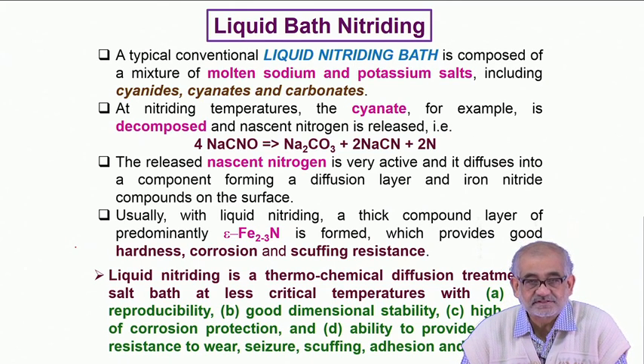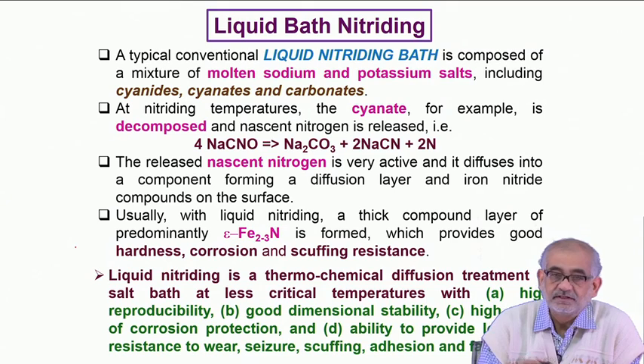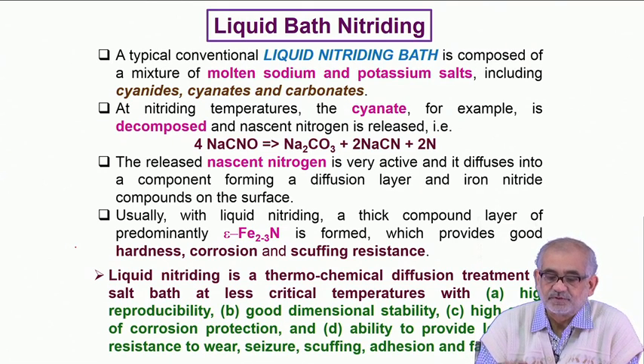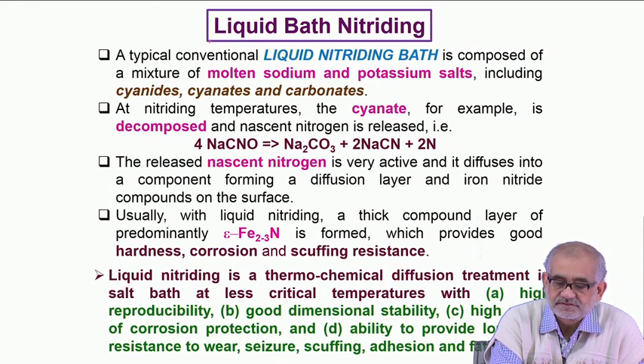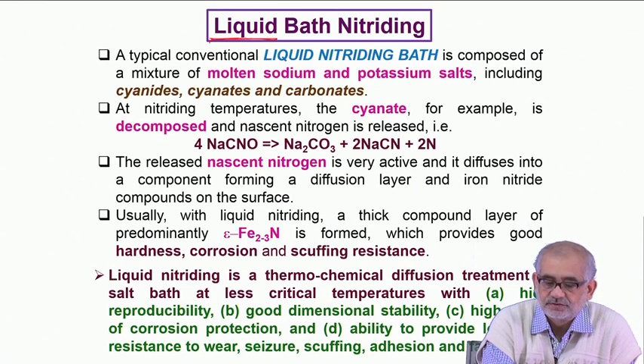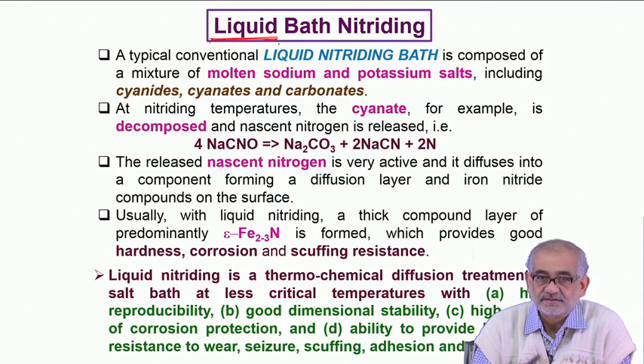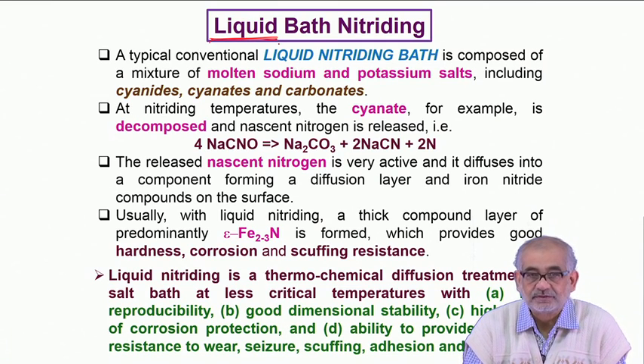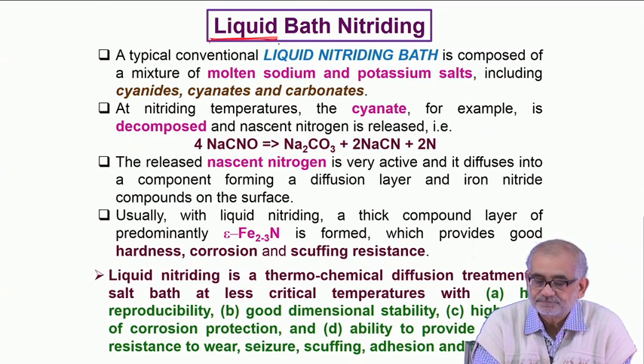So today, in the previous lecture we discussed gas nitriding, having nitrogen in the gaseous atmosphere. And today we are going to discuss liquid bath nitriding. So, we essentially have a salt bath, which we keep in the molten state, and then immerse the workpiece into the bath and allow the nitrogen to be liberated from the salts and then get absorbed and gradually diffuse into the bulk of the solid from the surface.